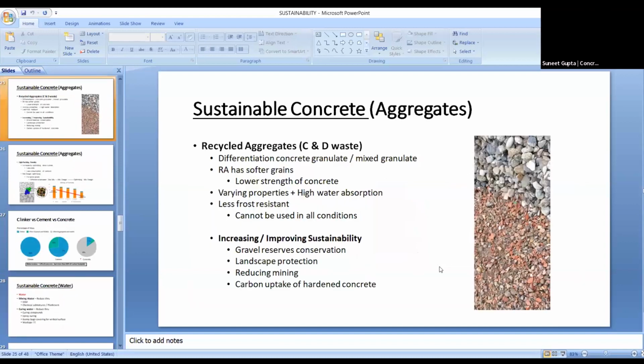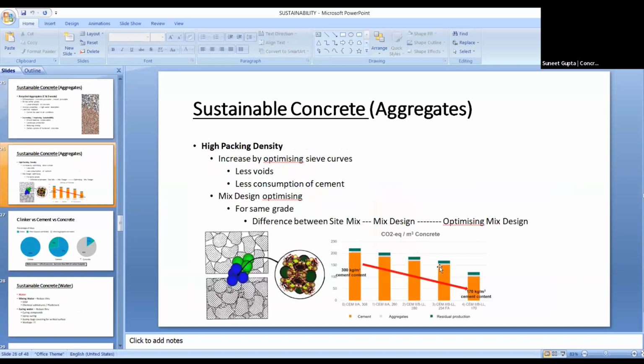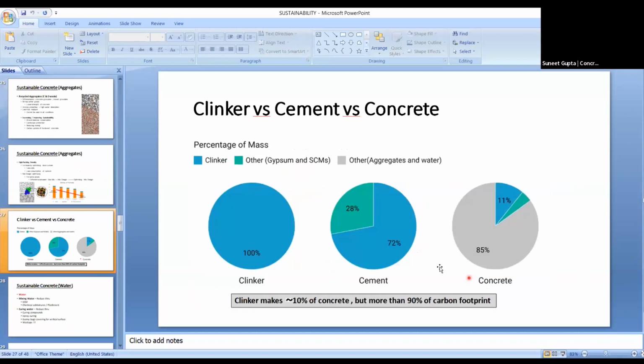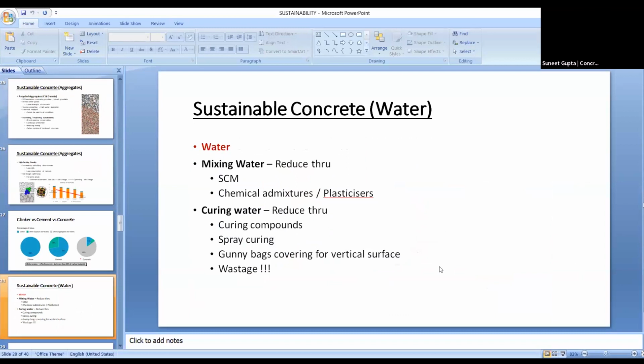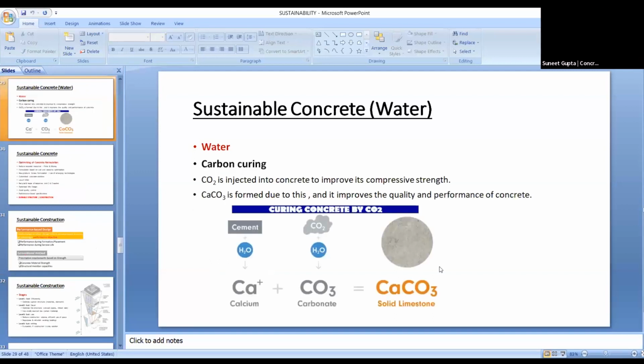The next thing I want to cover is recycled aggregates. We should stress recycled aggregates, though they have their own advantages and disadvantages. But as far as possible, we should use them. We should go with a high packing density of aggregates so that the cement consumption reduces. The clinker in concrete is hardly 10%, but its carbon footprint is more than 90%. When we talk about water, we can reduce mixing water and curing water. There are effective mechanisms, as I have listed, and there are more than those, but we should reduce the water also. And there is something called carbon curing also, which we can look at further.